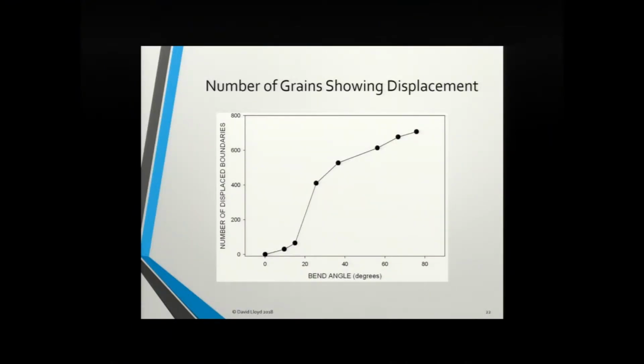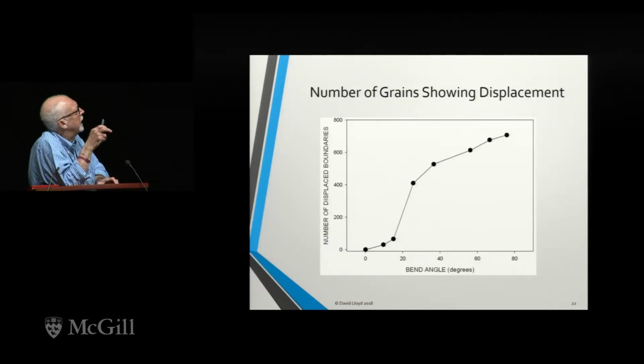The number of grains showing displacement with bend angle follows this trend. And you can see that the displacement starts from really pretty low bend angles, then increases very significantly, and then levels off. The number of grains increases, but also the displacement at the boundaries, on the individual boundaries, increases fairly drastically.